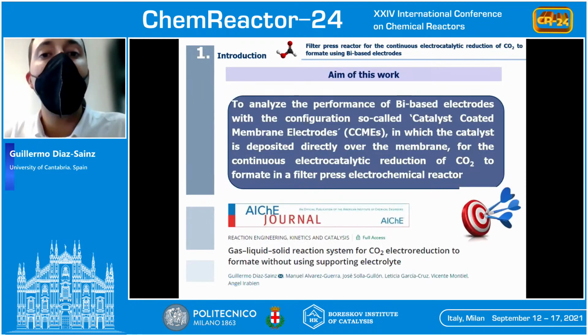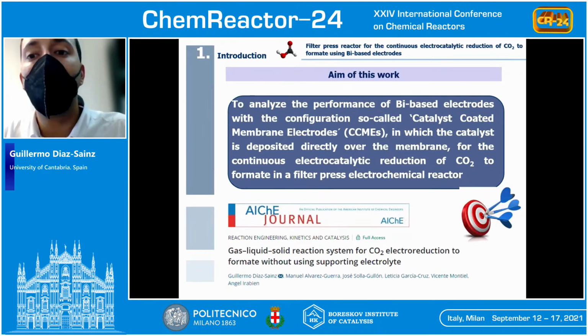In this context, the main aim of this work is to analyze the performance of bismuth-based electrodes with the configuration so-called catalyst coated membrane electrodes, CCMEs, in which the catalyst, in this case bismuth carbon-supported nanoparticles, is deposited directly over the membrane for the continuous electrocatalytic reduction of carbon dioxide to formate in a filter-press electrochemical reactor. It is important to highlight that in this case the membrane acts as a solid polymer electrolyte.